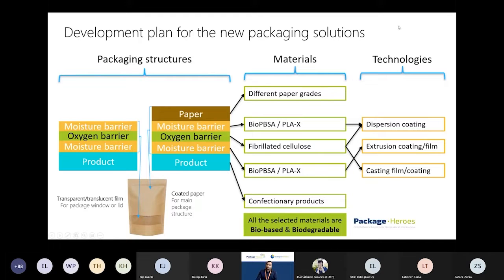And the technologies that we used for producing these multi-layer structures, they covered basically two main technologies: dispersion coating and the extrusion coating or film production. And for fibrillated cellulose, we also used cast coating method to apply slightly thicker layers where needed.